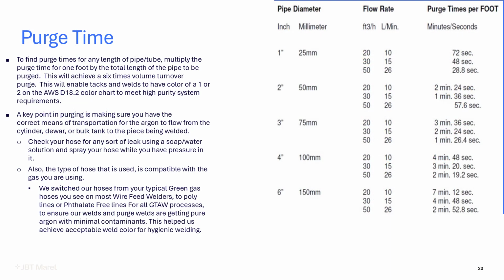To find the purge times for any length of pipe or tube, multiply the purge time for one foot by the total length of the pipe to be purged. This will achieve 6 times the volume of turnover purge. This will enable tacks and welds to have the color of 1 or 2 on the AWS D18.2 color chart to meet the high purity system requirements.